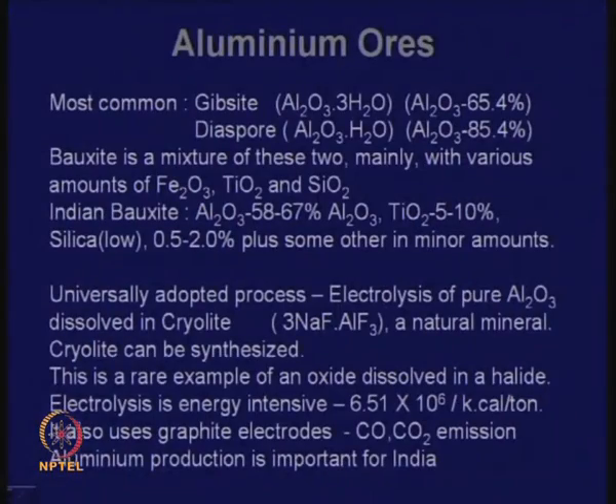You get a leach liquor, from there you precipitate alumina, then this alumina will be electrolyzed, dissolved in a salt called cryolite, which is written as 3NaF.AlF3 or Na3AlF6. It is a natural mineral, it can be synthesized also. Now, this is a very interesting example. Generally, oxides do not dissolve in halides. Halides dissolve in halides, oxides dissolve in oxides. It is a very rare example of an oxide dissolving, not completely, to some extent, in a halide.